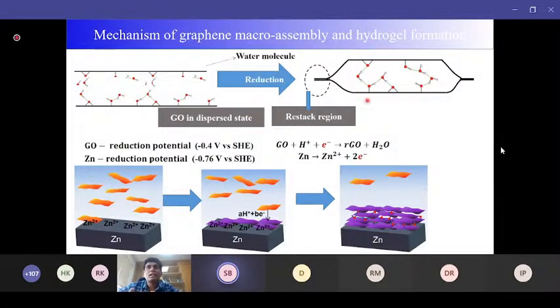This is what I showed you with two graphene sheets, but instead of two graphene sheets, millions of graphene sheets can be assembled like this. We have used some zinc plate here, some metal plate, and put it in the graphene oxide solution. Once we put it in the graphene oxide solution, due to the difference in reduction potential of graphene oxide and zinc, there is a spontaneous electron transfer from zinc to the graphene oxide. And this electron transfer actually reduces and strips off the functional groups from here, and it leads to chemically functionalized graphene.